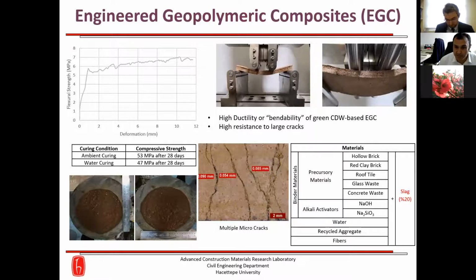After that, to further improve the properties of the engineered geopolymer composites, new mixtures were developed by replacing 20% of the precursor material with slag. So there is construction demolition waste, plus we have added a small amount of industrial waste. It is slag, blast furnace slag, around 20%. This replacement provided visible improvements in the properties of the mixtures. CDW is waste, slag is waste. We combine these two wastes and we obtain synergistic performances.